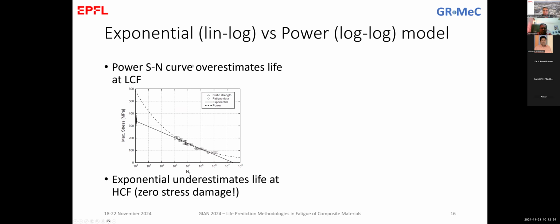On the other hand, the exponential model, which is what we call the lin-log, so the equation that is semi-logarithmic, it is a straight line in this semi-logarithmic diagram. We have the stress in a linear axis and the number of cycles in a logarithmic axis. So it is a straight line, which means that if we continue and try to extrapolate our fatigue data, we do not follow the trend of the data, which tend to be asymptotic to the x-axis, but we actually go and hit the axis here, which means that according to this modeling, the material should fail at zero stress when it is at 30 million cycles, which of course physically it's not correct, it's not acceptable.